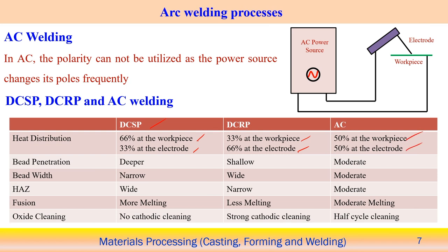If you compare the bead penetration, definitely at the workpiece the heat generation will be much more, so we can expect the penetration will be much more in this particular case. But in DCRP, we can expect shallow penetration, and with alternating current there is an equal effect on the electrode and workpiece, so in that case we can get moderate penetration of the weld bead. Bead width, in the other way: when the penetration is deep, the bead will be narrower, but in case of DC reverse polarity the bead width will be wide, and with AC current it is moderate.